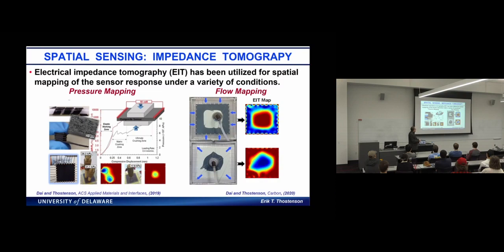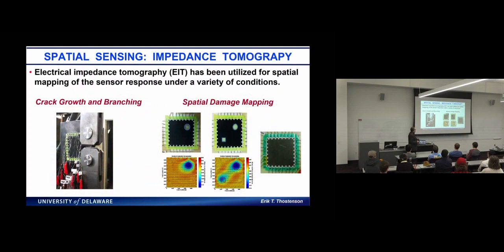flow, and our current Department of Energy project is looking at utilizing this for the liquid molding and doing this sensing in real time, so that if a defect is forming, say there was a dry spot, here we're injecting from the edge, and you see our conductivity map. If there was a dry spot to form, we could change the flow or try to force that into a different direction. And this is just, again, showing this kind of spatial damage mapping. So we've used this for sensing. And then what I'll talk about next is utilizing composites for structural rehabilitation, but also sensing.